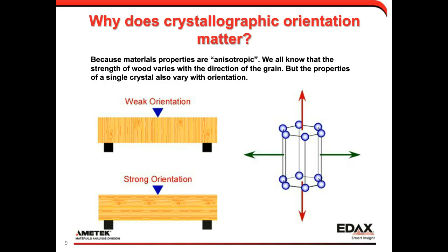And OIM and EBSD really ties into the crystallographic aspect of materials. Most materials are generally anisotropic, and by that I mean they vary with orientation. The easy way to understand this is to think of breaking a piece of wood. Shown on the left, if I want to look good when I'm doing my karate moves, I align the wood block so it's in a weak orientation. The grains are aligned with the direction of force. If I want to play tricks on my kid, I arrange it the other way so that the force is perpendicular to the long grains, so it's in a stronger orientation. And the same force will introduce different amounts of damage.